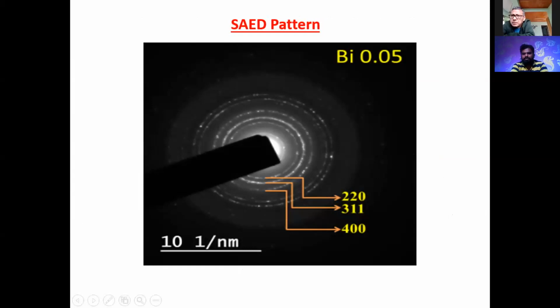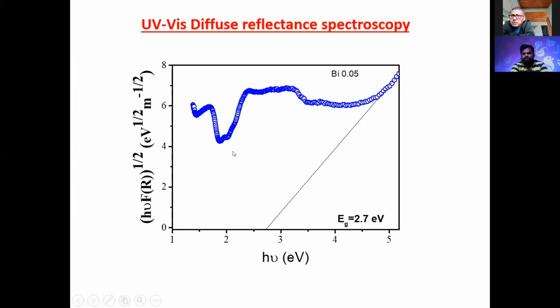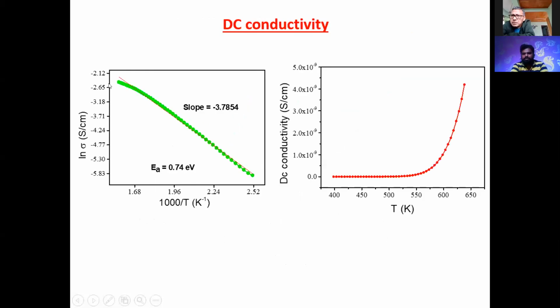This is the UV diffuse reflectance spectroscopy. This was studied using the Kubelka-Munk relation. The Kubelka-Munk function F(R) is equal to (1 minus R) whole square divided by 2R. From UV diffuse reflectance spectroscopy, we have calculated the energy gap of the sample. This is the DC conductivity. The first graph is the Arrhenius plot. From the Arrhenius plot, we have calculated the activation energy of the sample: minus Ea is equal to slope into Boltzmann's constant. The DC conductivity versus temperature graph clearly shows that as temperature increases, conductivity also increases.